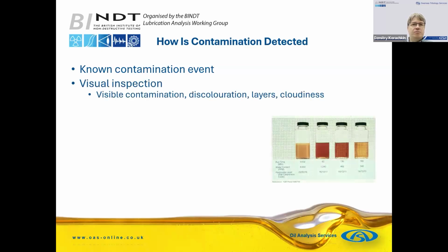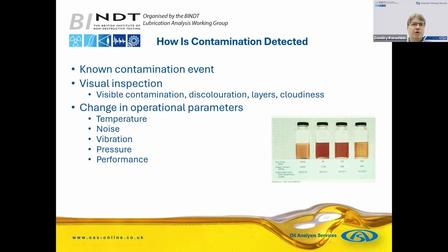Maybe visual inspection, either through an oil sight glass, where we can see discoloration, cloudiness, or changes in the appearance of the oil, or we may see contamination on the surface of the equipment, or we may see that the hatch to the oil tank is open, and this will likely allow some contamination to get in.